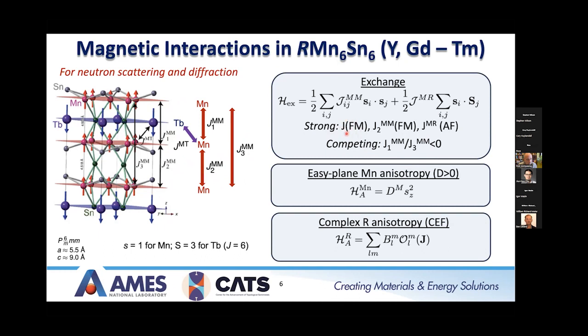So as I said before, J, the intraplane interaction for the manganese, is strongly ferromagnetic. J2 is ferromagnetic. Of course, this rare earth manganese interaction wants to be anti-ferromagnetic, and then you have this competing J1, J3, and depending on the relative signs of J1 and J3, you get differences in the magnon spectrum, which you can detect readily using our inelastic neutron scattering. All right, so we have the easy plane manganese anisotropy, of course, also within this Hamiltonian we're building. And then you have the complex rare earth anisotropy that depends on the crystal field splitting.